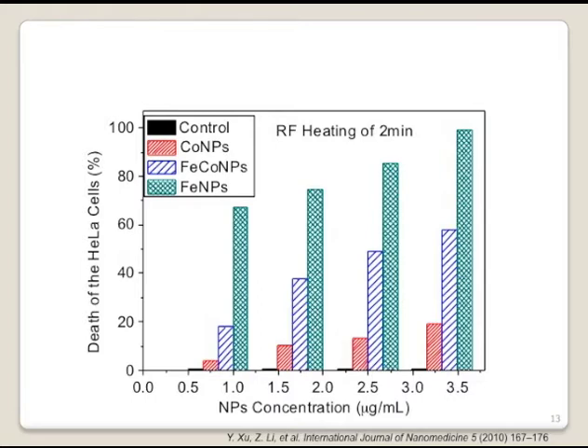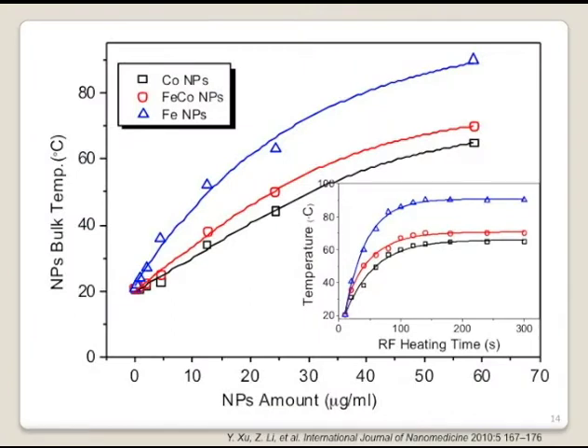Okay, how does the temperature of the nanoparticles change under the RF heating? Here I have time. You can see that 5 minutes is enough to highlight the heating rate and the induction temperature of these nanoparticles. This blue line is the iron nanoparticle. It's much more efficient. They can reach almost 100 Celsius. It's 93 something Celsius, right?